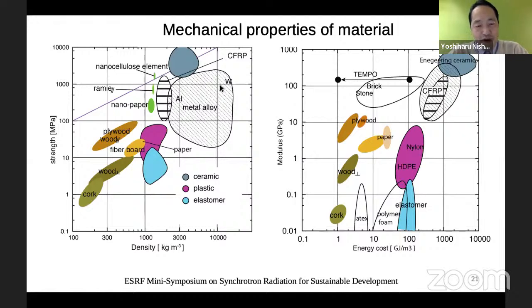Another point we are looking at is the mechanical properties. So this is an example, a graph showing general trends of different types of materials as a function of density. For example, this is strength and density relation. And when we look at this example of wood materials, what we also know is that wood is strong along the grain, but there is about 10 times difference between the strength along the grain and perpendicular to the grain. And in general the strength is proportional to the density of the material.